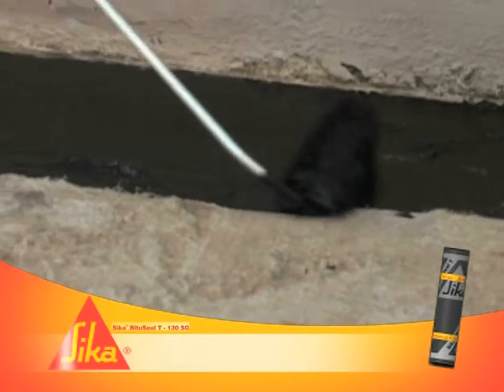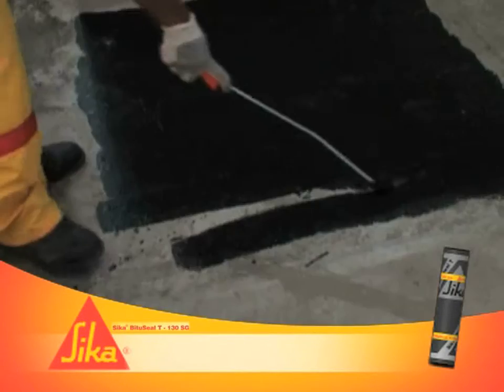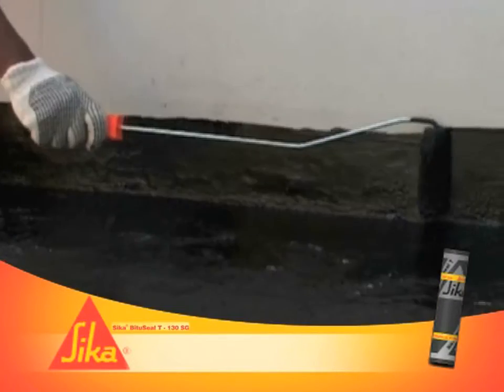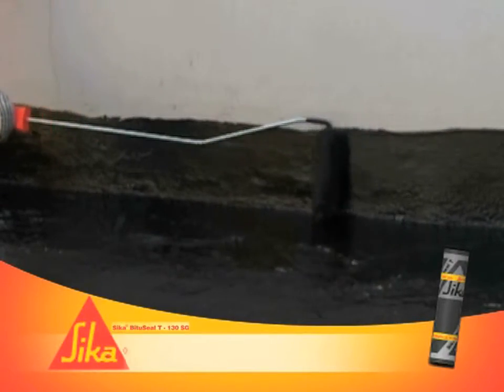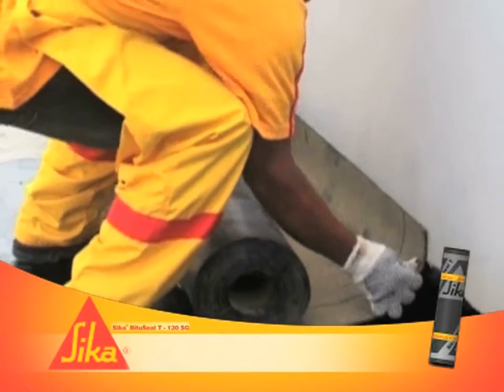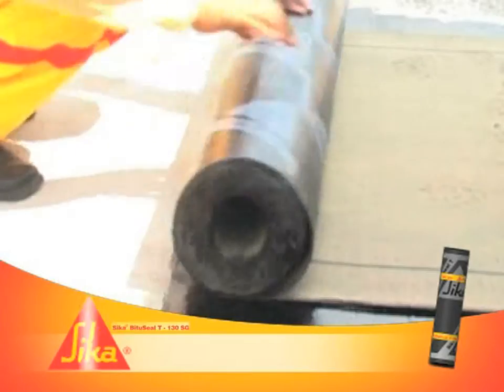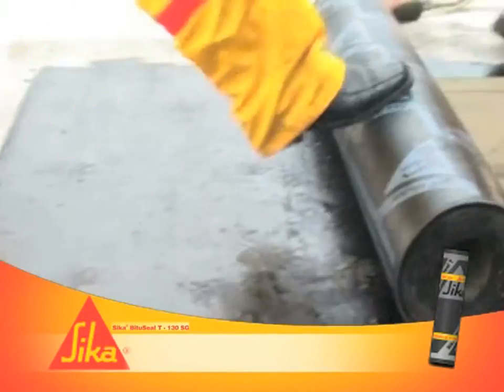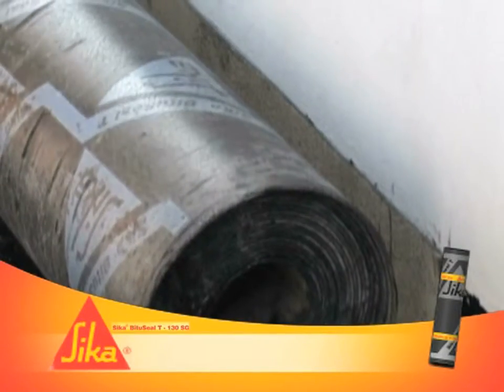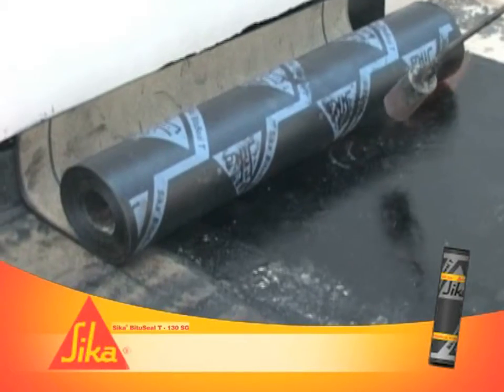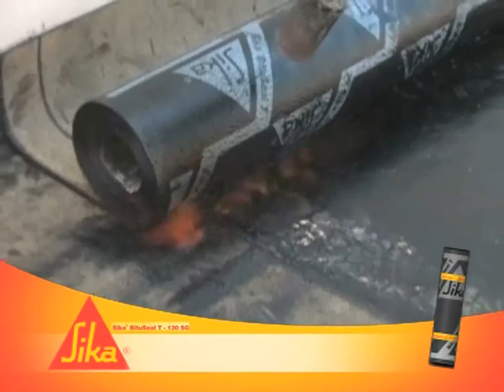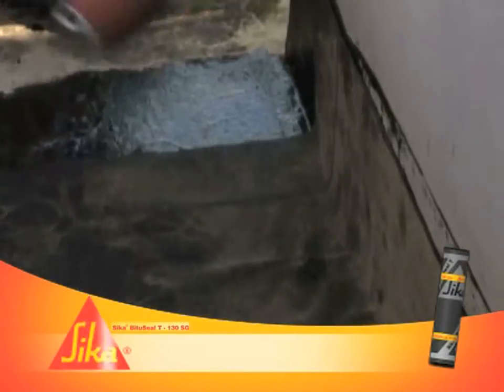Apply bituminous primer with a brush, roller, or spray. The waiting time is approximately 4 to 6 hours. Lay the membrane with a polyethylene film facing the substrate. At the same time, bond the membrane to the substrate with a torch-on method using a gas torch.